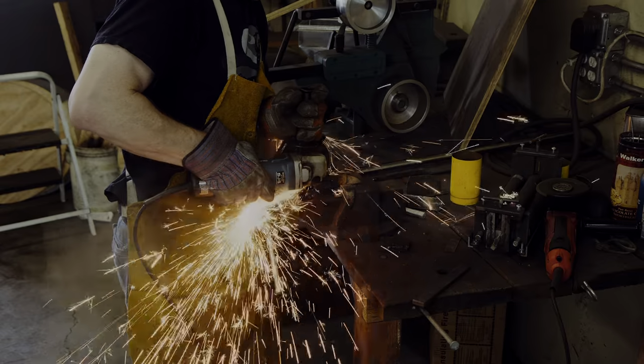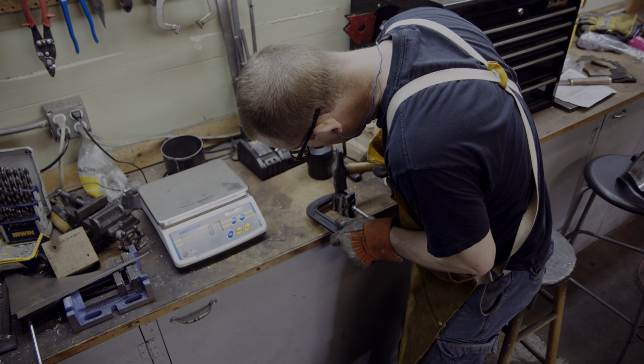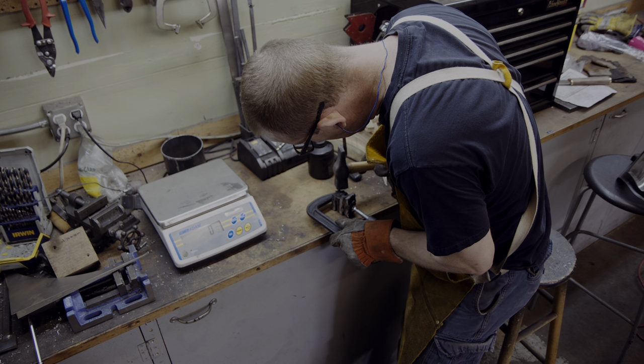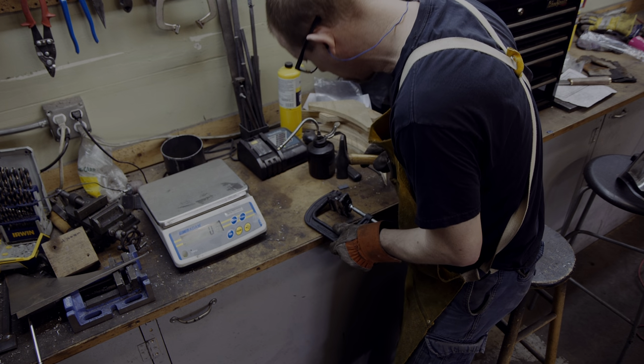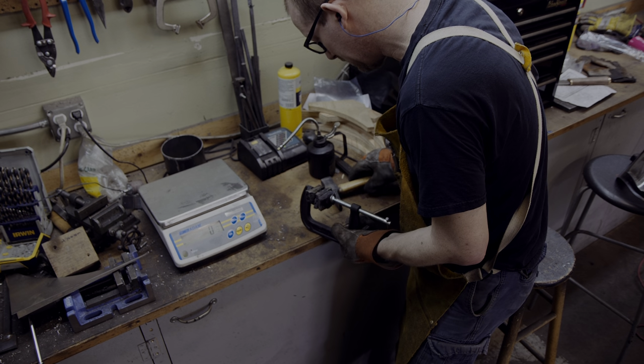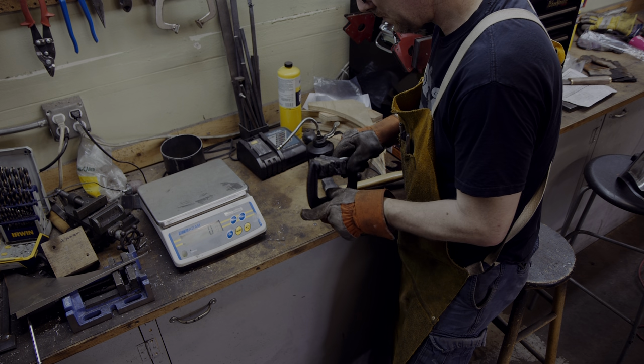To test the quality of the welds, I upset the billet. Unfortunately, it showed that there were pockets inside of the billet that had not welded. I am cutting them open and hope that one more round of very hot forge welding might take care of it. At least, I still have enough material to make a knife-sized billet.